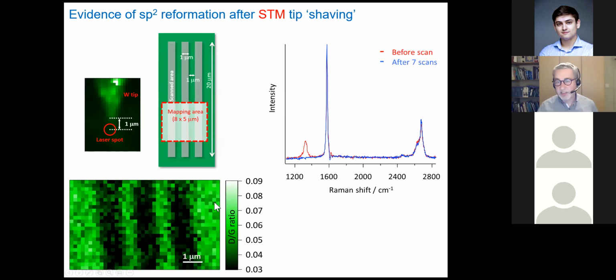Of interest is that if you do this nanolithography, in the areas where we have nanoshaved using the STM tip, where we have removed the molecules, at least that's what we claim, if we look in such an area with Raman spectroscopy, the D band, which is typical for a covalent functionalization, has completely disappeared. So we believe that by this lithography approach, we can locally regenerate graphite or graphene, creating the sp2 bonds.